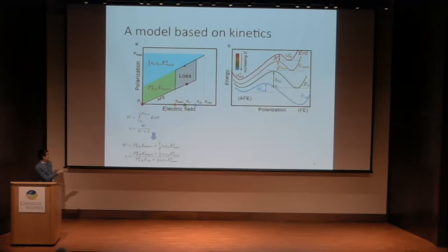And the antiferro to ferro transition happens when the ferroelectric phase has a lower energy, and this kinetic barrier, delta ER prime, can be overcome by the thermal energy. Something similar applies to the ferro to antiferro transition. Because these two barriers, delta E down and delta ER prime, are both limited by the same temperature, we will assume they are the same. Without showing all the details, the final expression is this.